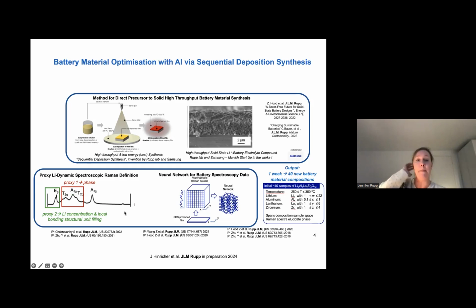This is a Raman spectrum of the lithium garnet structure. And if it's highly conductive, it's a cubic phase. And there are two features you can use later for probing as proxy definitions. One is: is it the right phase? For instance, if I make hundreds of those materials at very different conditions, then some may be in the cubic phase, some may be in another phase, right? And I want to get the fast conducting one. So I could probe it by just looking at those signatures here, the T2G, A1G, and T2G in the spectra. And if I look at the lower wavenumber bands, the EGs, I can learn a lot about the lithiation level and about the oxygen-lithium-oxygen bonding in it. So there's also this level at which I can directly access information.